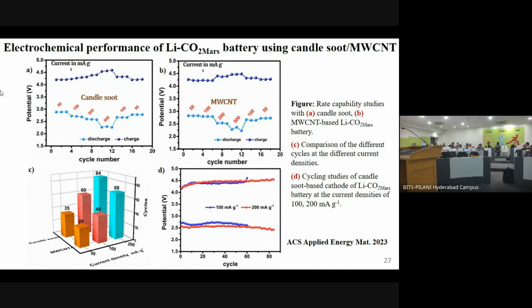This is what you see in terms of performance of candle soot and multi-walled CNTs at different current densities. In all the different current densities, what we see is that the overpotential for the candle soot is less than the overpotential for the multi-walled CNT, which means the candle soot is working more efficiently. Not only that, in terms of total number of cycles which we can achieve, at any current density, let's say for 50 milliampere per gram, candle soot had higher cyclability, 35 as compared to 28, and at 200 milliampere per gram we were able to achieve 84 as compared to 68 for the multi-walled CNT.